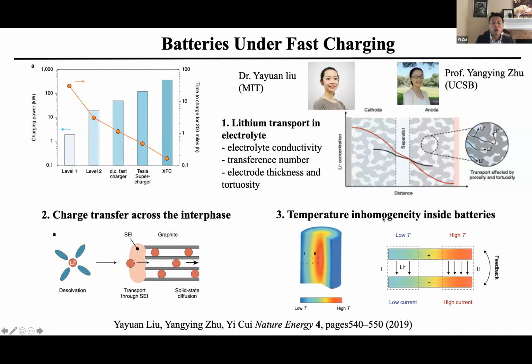The next thing is that temperature inhomogeneity will build up. I'm showing a cylinder cell right here, but a pouch cell will have a similar effect. The center of the battery will get hotter, while the outer surface approaches room temperature, so you are going to have a temperature gradient inside the battery cells. Certainly higher temperature will give you faster kinetics and higher current, but higher current will also drive heat generation even more. So this can become a positive feedback loop. And the higher temperature part will get cycled, charged and discharged more. The current density is higher compared to the lower temperature part. This can potentially create issues.